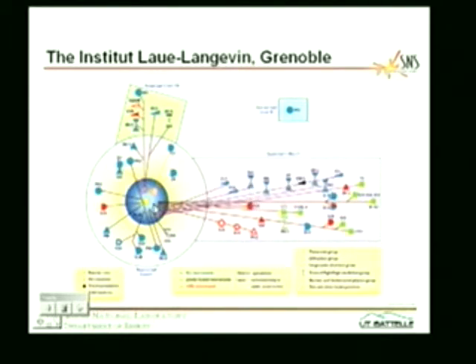And it's got cold sources, 2 of them. This is the newest one, which is a great big liquid deuterium cold source. It's also got a hot source, which is just a lump of graphite that's placed adjacent to the reactor core, and it gets just heated up by the gammas to about 1500 degrees, and that shifts the Maxwellian spectrum the other way. So if you want short wavelength neutrons, then you sit on this hot source. If you want cold long wavelength neutrons, you sit on the cold source, and if you can't make up your mind, then there's thermal beams as well.